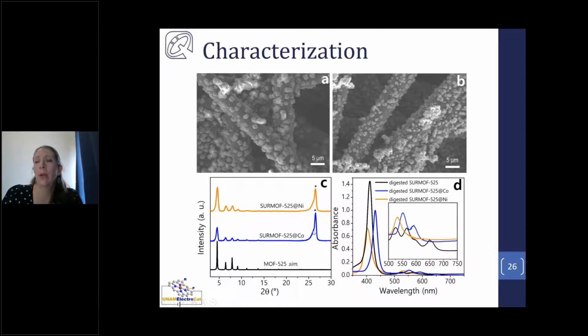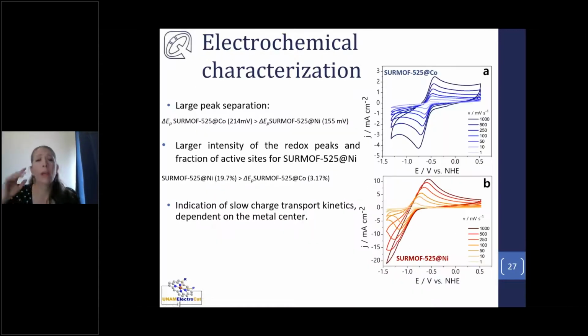We also carried out X-ray diffraction, where we see the crystal structure is that of the MOF 525 as expected, and UV-vis measurements confirmed that the MOF was completely metallated. Then we moved to the electrochemical characterization, and for that we carried out cyclic voltammetry. We can see the redox peaks for the metal centers, so cobalt and nickel. What we observe is that the peak separation of the oxidation and reduction process is quite large. It's larger than what we would expect by the Nernst equation, which points towards a slow charge transfer mechanism.